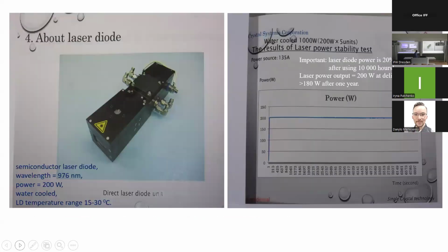How a laser diode looks like: it requires very powerful water cooling. So there is a special separate water chiller that we need for cooling of the running lasers. The wavelength is about 1 micrometer, and the power of each laser is around 200 watts. Important that the laser power output is very stable with time, although there is a small, I would say, aging effect, but the time scale is over 1-2 years.